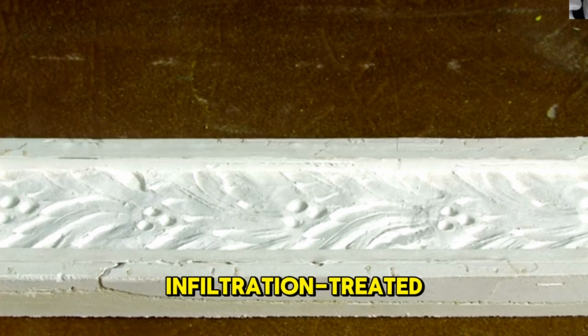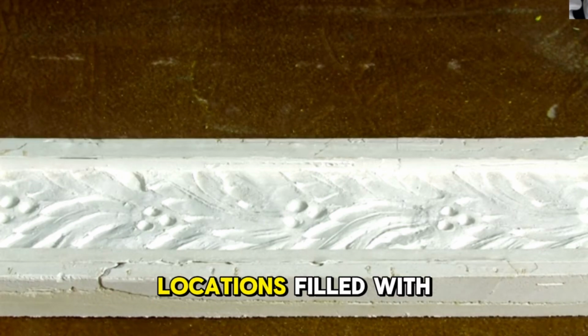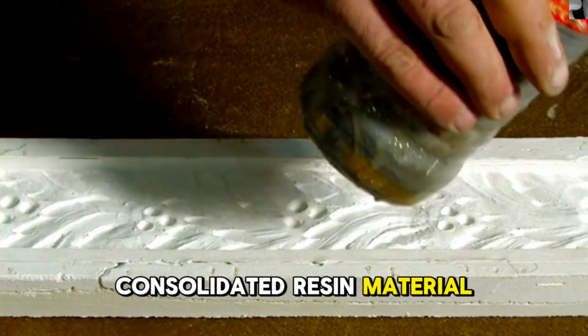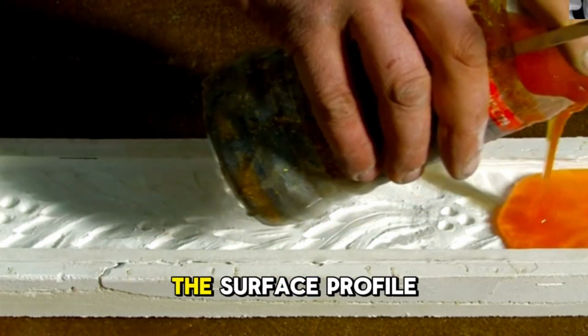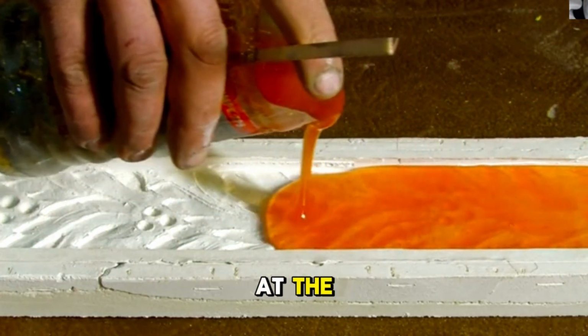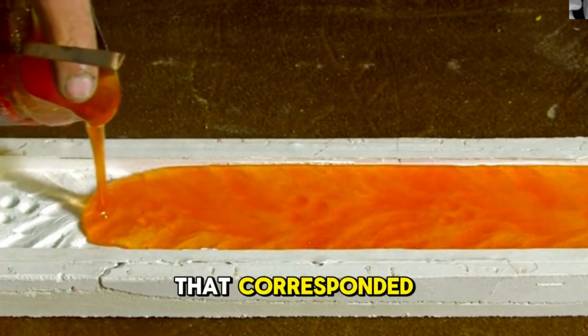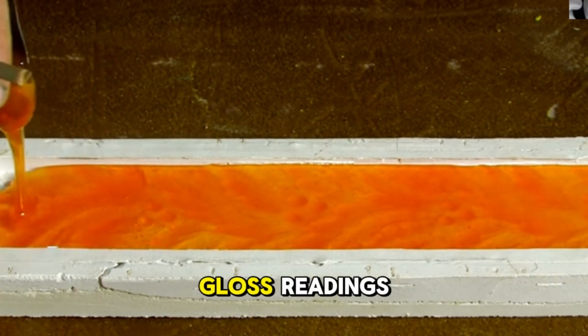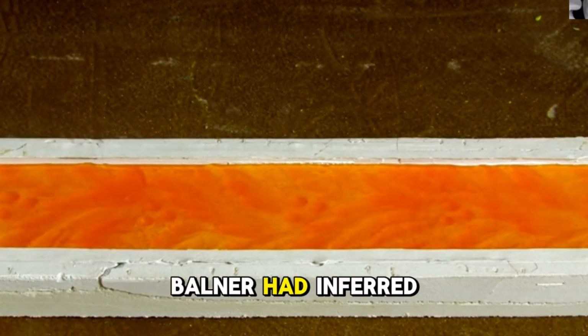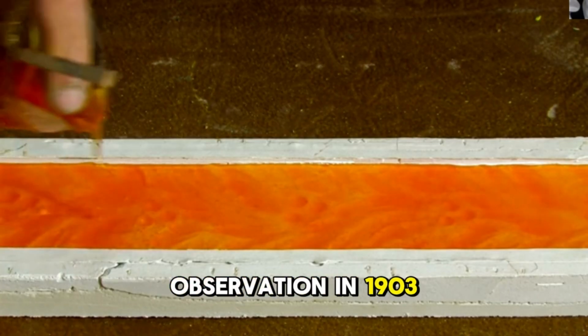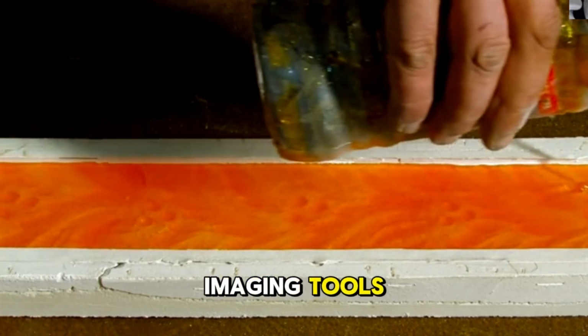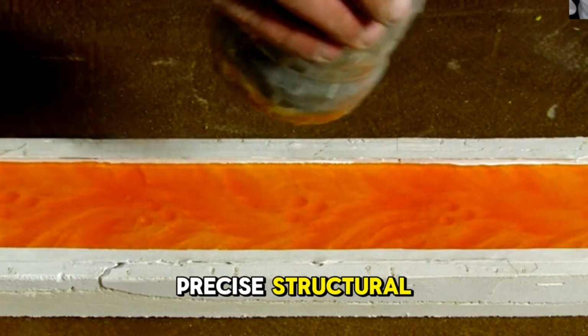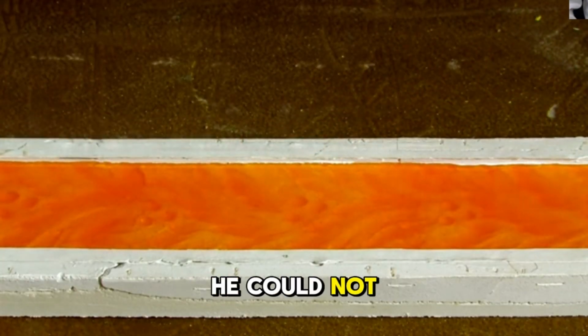Cross-sections of the infiltration-treated panels showed the same fracture locations filled with consolidated resin material, the channels bridged and sealed, the surface profile smoother and more uniform at the microscopic scale in a way that corresponded directly with the improved macroscopic gloss readings. The mechanism Ballner had inferred from observation in 1903, without access to any of these imaging tools, was confirmed in precise structural detail a century later by equipment he could not have imagined.